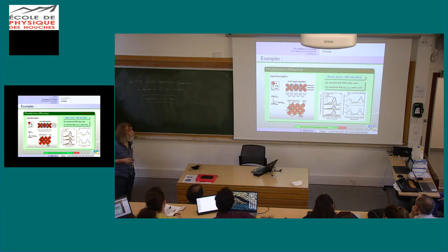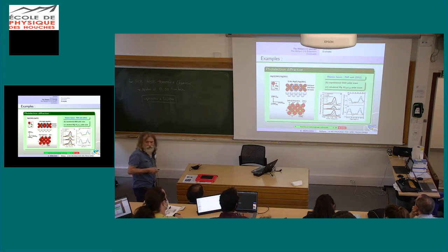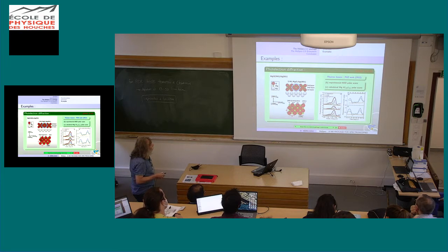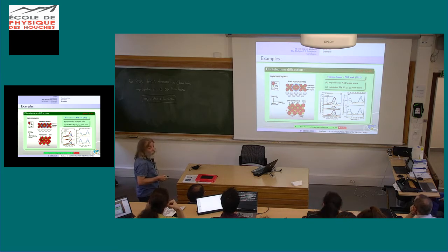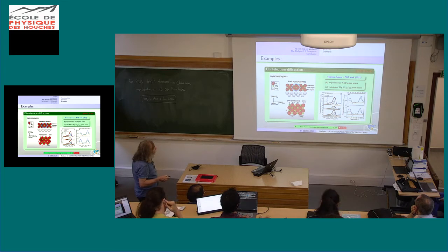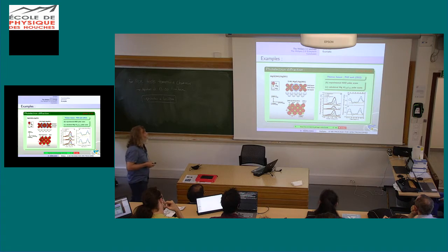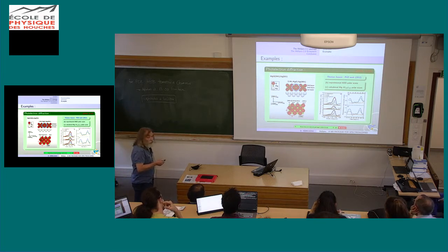Here you've got the peak for different positions of the analyzer. If you do the angular variations in theta — the polar variations of the given peak — you see that they have quite different modulations. The first thing to do was to see if we could reproduce this by calculation in order to validate the decomposition and validate the method. You see that this is the experiment and this is the calculation, and with MSPEC you can reproduce fairly well what is obtained from the experiments. That's a benchmark to test the feasibility of what we want — studying something at the interface between these two materials.